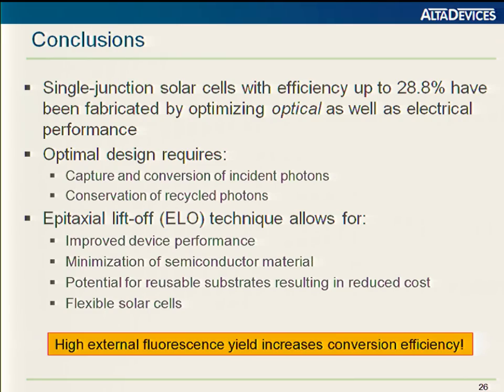With that, I'll conclude. We've fabricated a 28.8% efficient gallium arsenide solar cell by optimizing the optical properties of the cell. We tend to think of our cell primarily as an optical device. The optimal design requires not only capturing and converting the incident photons, but making sure you don't lose the photons that are emitted within the cell. We use the epitaxial lift-off technique to achieve this.